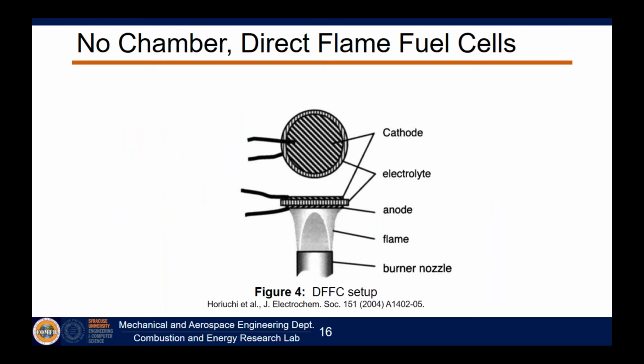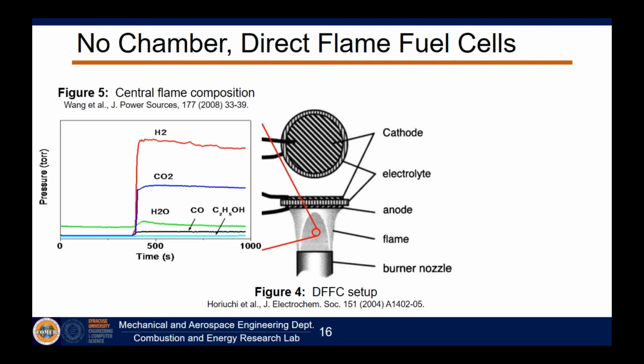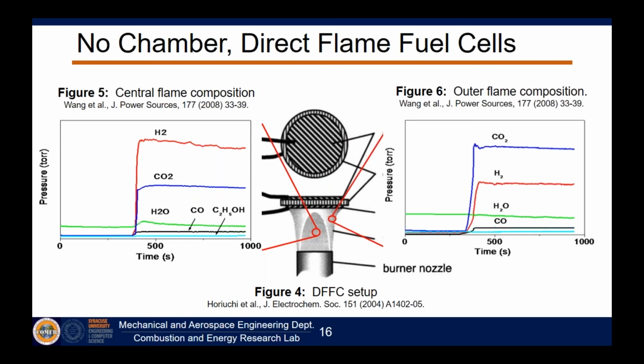And actually a lot of work was done just looking at what kind of burner would optimize this kind of system. Turns out that within the flame, you can find significant amounts of hydrogen, right? And some carbon monoxide. CO2 doesn't hurt the fuel cell, but it doesn't help either. It just kind of dilutes the fuel. So ultimately, if we're in certain locations, we can find quite a bit of hydrogen that we might be able to convert to power with the fuel cell. But if we're in other locations within the flame, that composition changes significantly. In fact, as you get closer to these edges, you can see it yourself. There's air everywhere, right? This is an open flame.